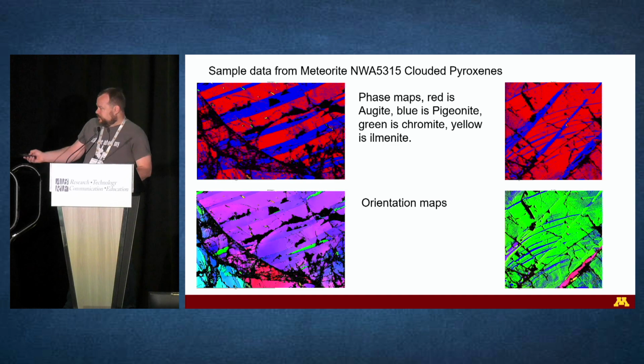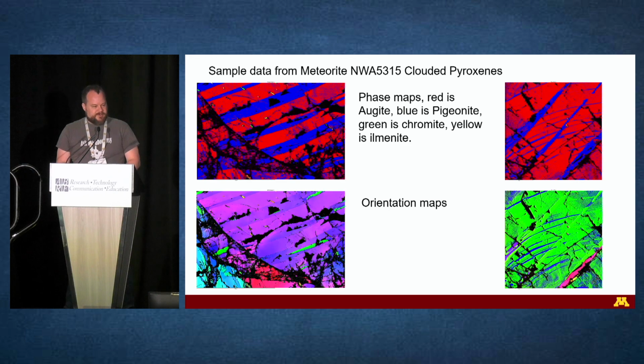The other interesting thing we found in this sample here, normally the red and blue minerals will separate from each other in these nice straight lines. They're crystallographically controlled. Unfortunately, in this area, we found some curved ones. We have no explanation for what those are yet, but we're working on a paper for that. Not quite sure how you can make a curved crystallographic plane when the others are straight.